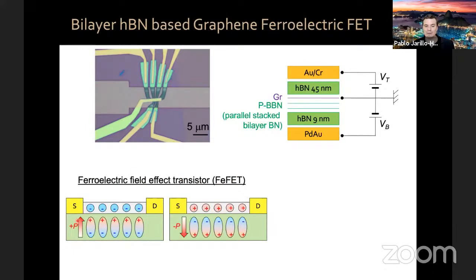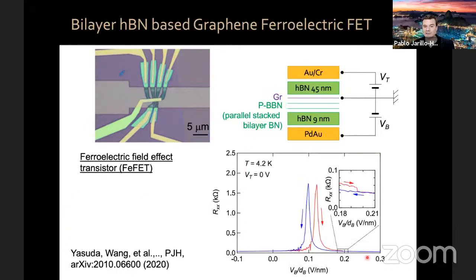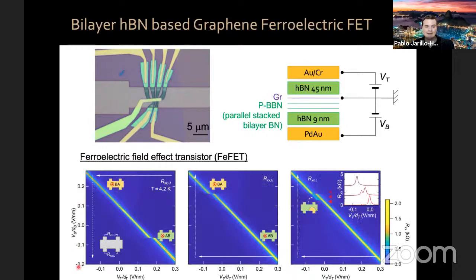If you have a given dipole moment for your ferroelectric, there will be a type of charge carrier in your system. If you have the opposite dipole moment, you will have the opposite charge carrier. And indeed, if you measure such a device and you measure the resistance as a function of the backgate voltage, you can see that if you sweep your backgate voltage in one direction, you have a resistance peak of graphene. If you sweep back in the opposite direction, this resistance peak is shifted. You have hysteresis. You can look at this hysteresis in a two-dimensional plot of the back gate and the top gate. You can see this diagonal is telling you the graphene charge neutrality resistance point, which switches abruptly when you go from BA to AB configuration. You now reverse your measurement. This switches back at a different point in this diagram. There is hysteresis. Sometimes we're able to catch the coexistence of AB and BA domains, and we have a double peak in your resistance. Now, this was for parallel stacking, 0 degrees angle.